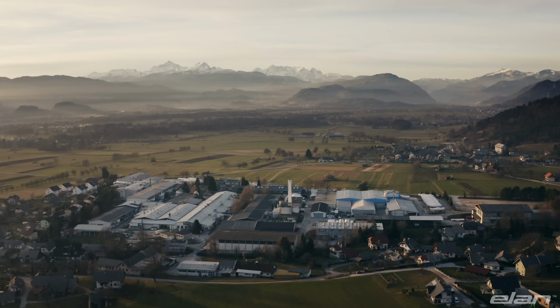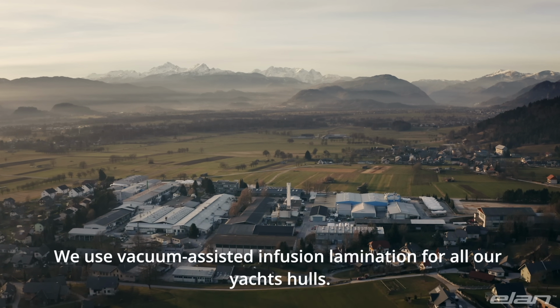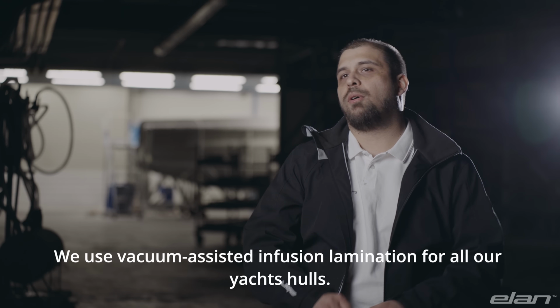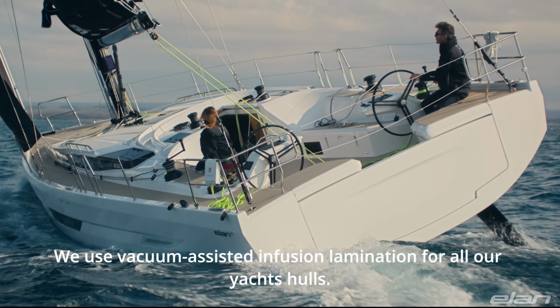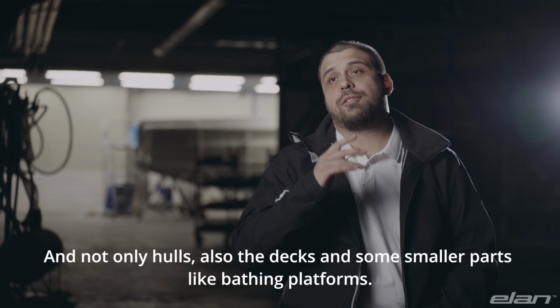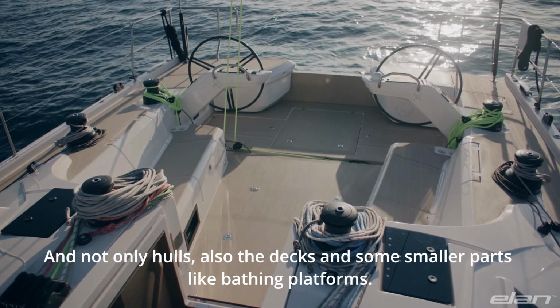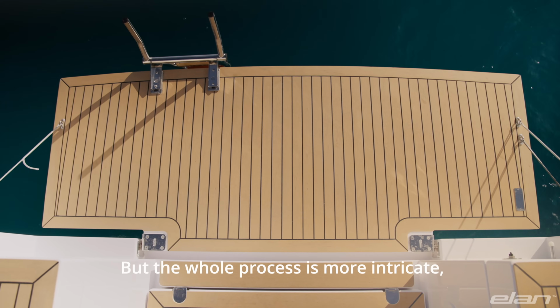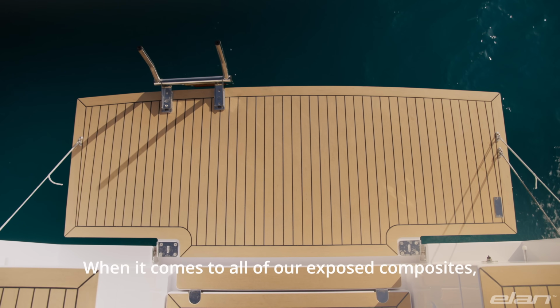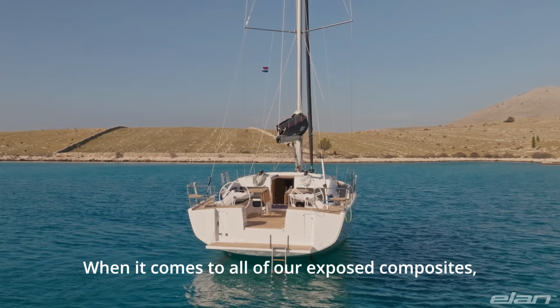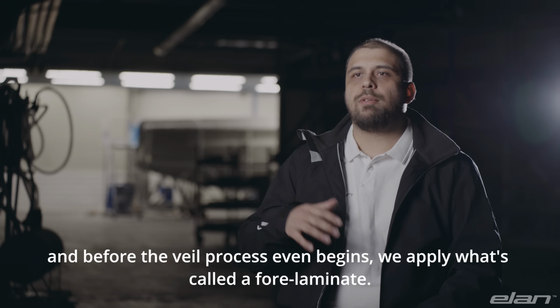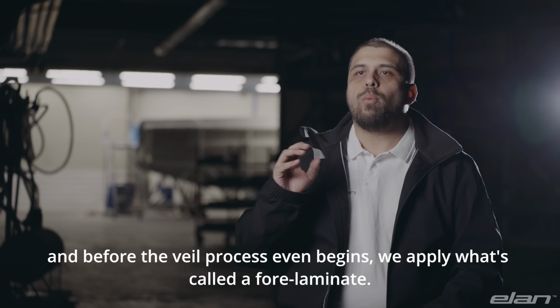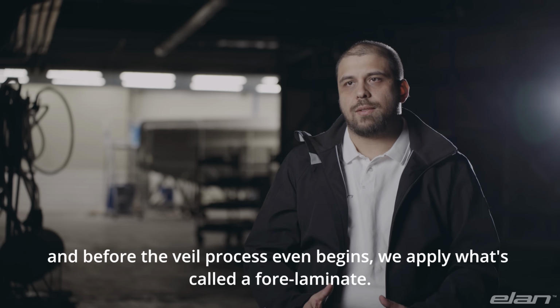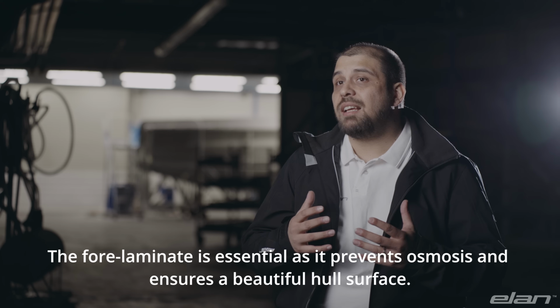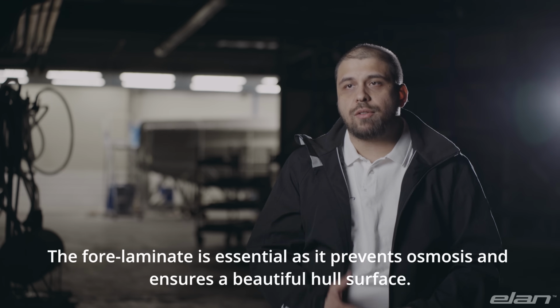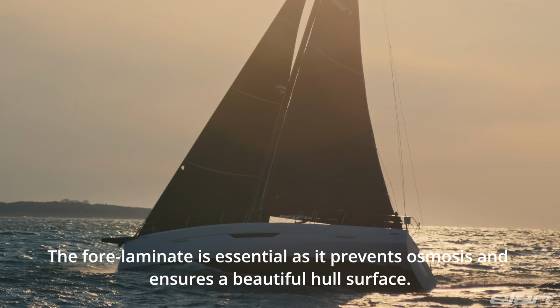to the environment. We use vacuum assisted infusion lamination for all our yacht hulls, and not only hulls, also the decks and some smaller parts like bathing platforms. But the whole process is more intricate. When it comes to all of our exposed composites, and before the VAIL process even begins, we apply what's called a fore laminate. The fore laminate is essential as it prevents osmosis and ensures a beautiful hull surface.